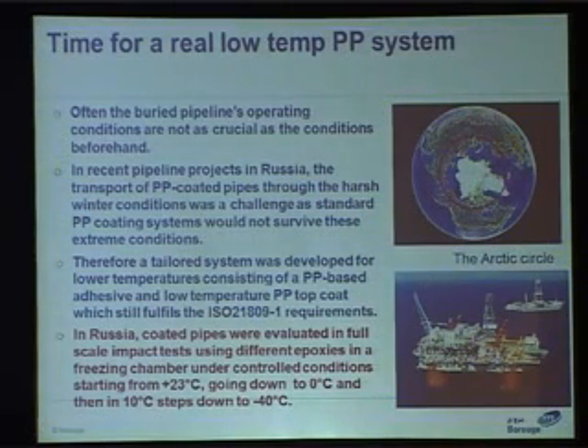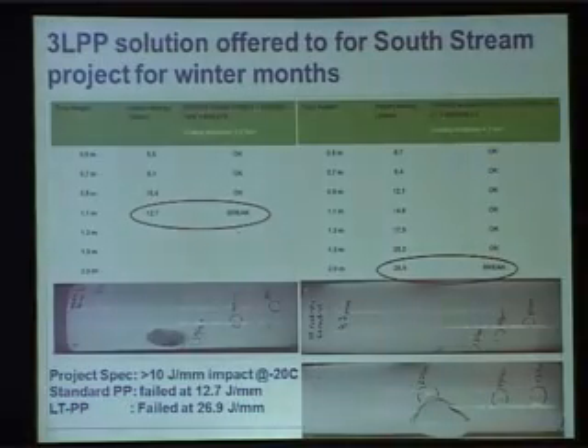In Russia, coated pipes are evaluated at full-scale impact tests using different epoxies in a freezing chamber under controlled conditions, starting at 23 degrees centigrade, going to 0 degree, and then in 10 degree steps down to minus 40. The South Stream project spec was more than 10 joule impact per millimeter of coating thickness at minus 20 degrees centigrade.